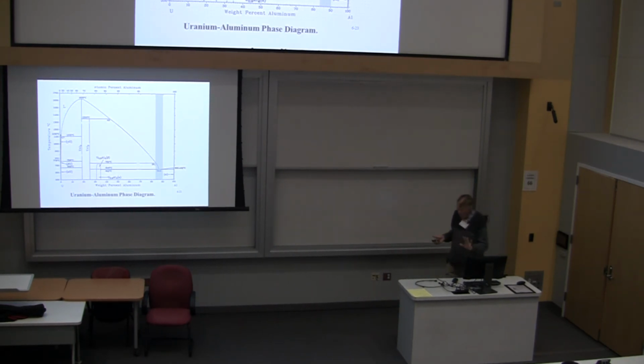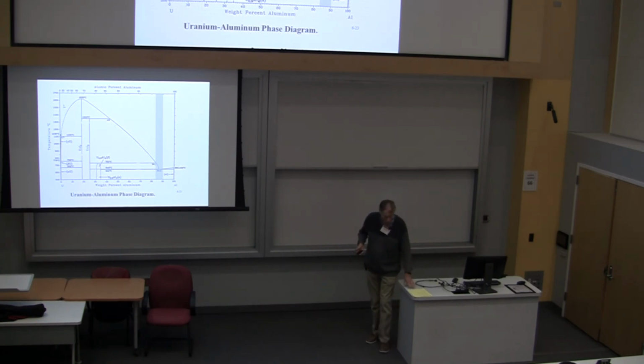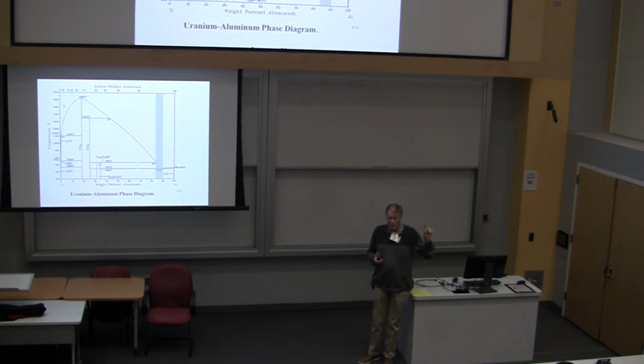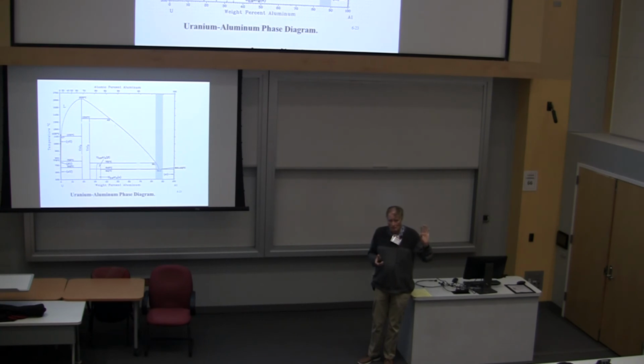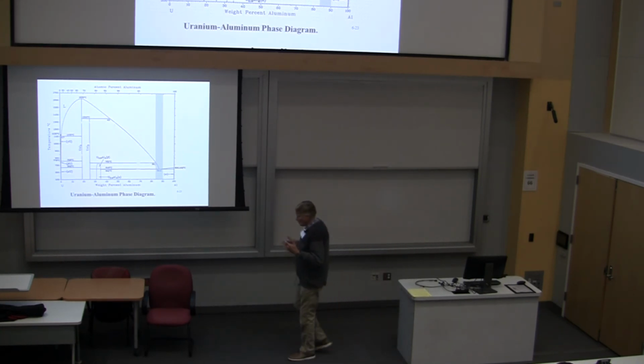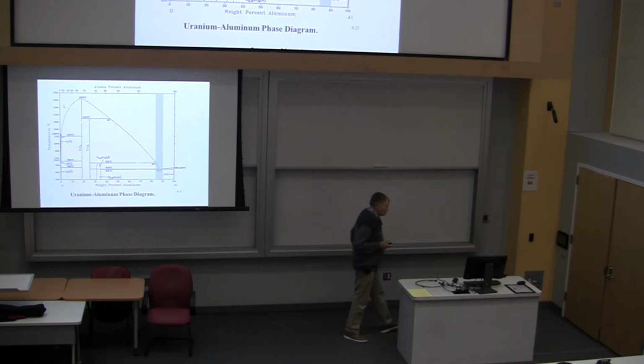But it turned out ultimately that you don't need to use a beryllium crucible. The beryllium dissolved in aluminum does not attack those crucibles, and that was something that was learned later. The other thing, and this is germane to something you should keep in mind when flux growing, is that it turns out that aluminum can substitute on one of the beryllium sites. There are two beryllium sites in there, a 12 site and a 1 site. And you tend to get some aluminum substituting on that other site. This is something you have to be aware of when doing flux growth.